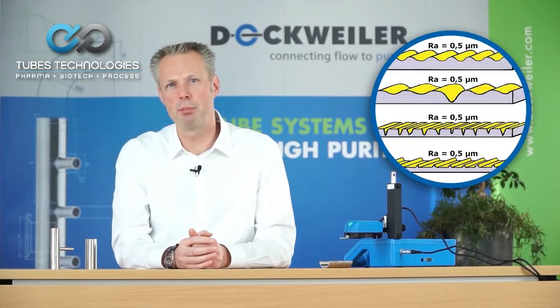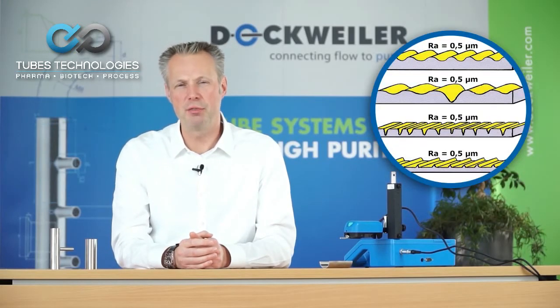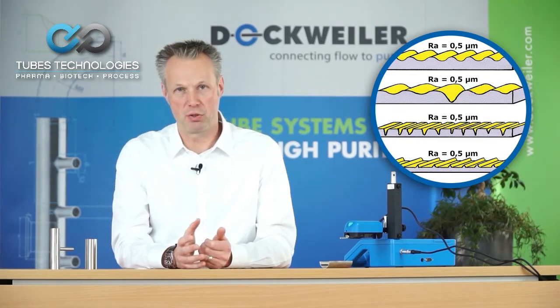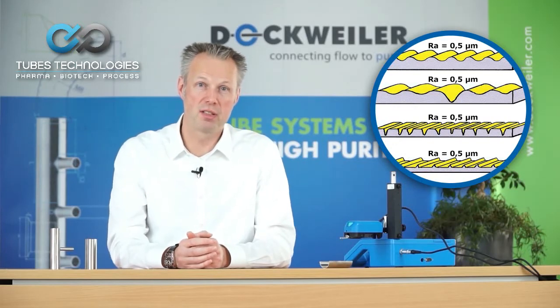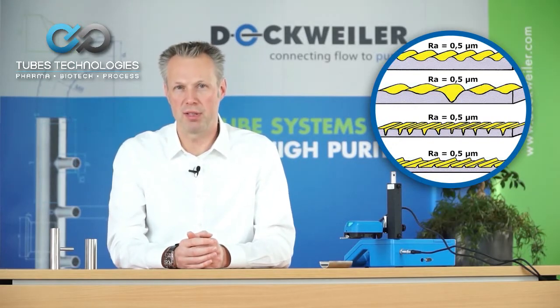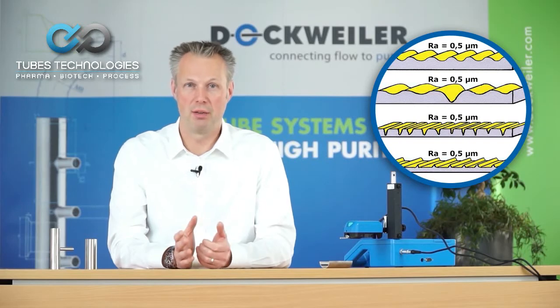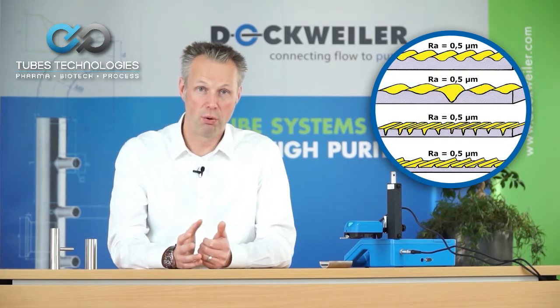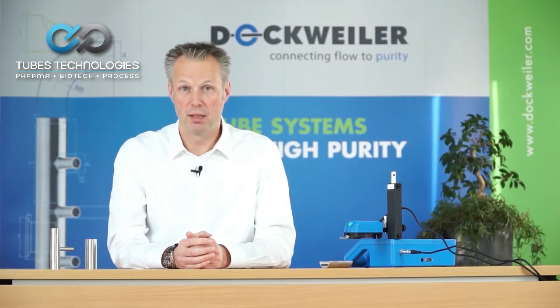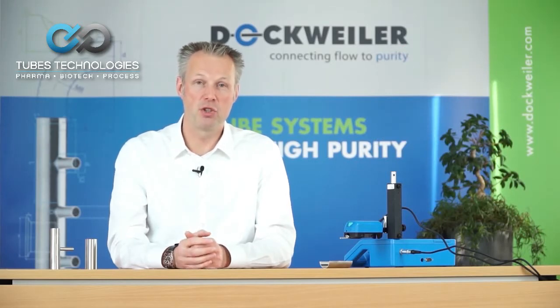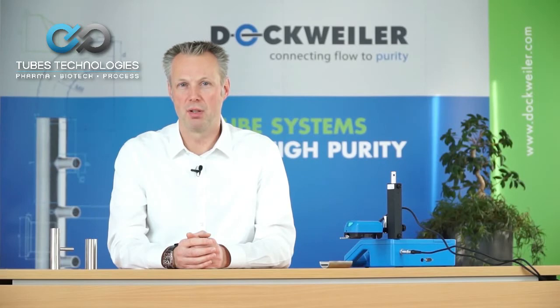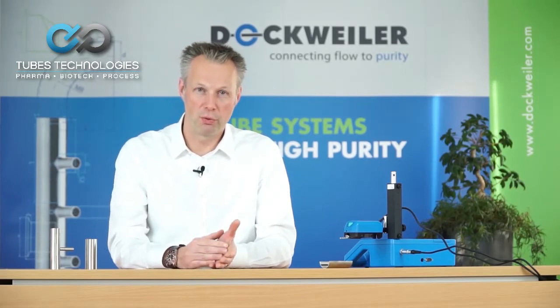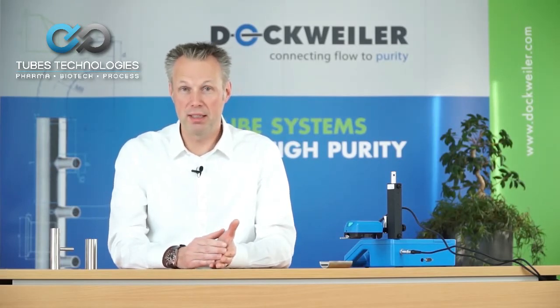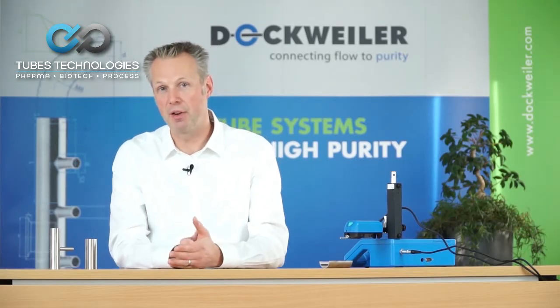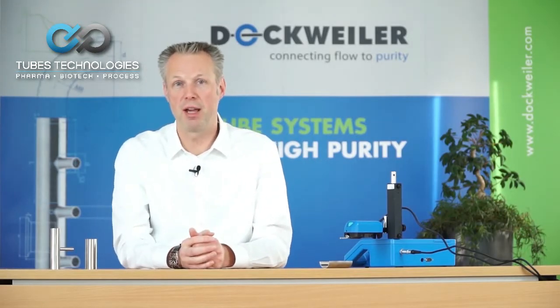Furthermore, when you see this upper picture, you see different surfaces which show you the same RA value. But certainly all these surfaces have different cleaning properties, as you can see. The upper one is pretty easy to clean, the lower one is pretty difficult to clean. But that is also an indication about the quality of a surface. So with this picture you can see that on the one hand the quality of a surface, the cleanability of a surface, and RA value do not have that much in common.